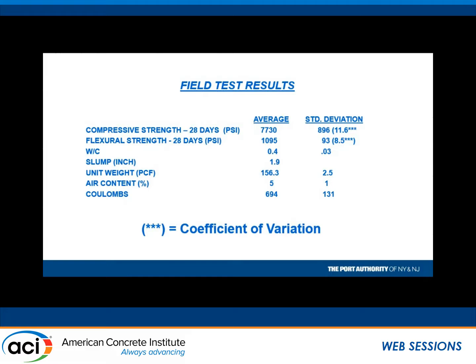And again, people were saying that making the modulus of rupture, C78, a lot of variability in that test. So we said, well, let's see how much variability we got there compared to C39. You see those numbers there? Compressive strength for this concrete, now again, this was up to 10% of the concrete had plus 2-inch stone, 7,700 PSI compressive strength. Flexural strength, almost 1,100. Look at the coefficient of variability. It was higher for the C39 test than the C78 test.